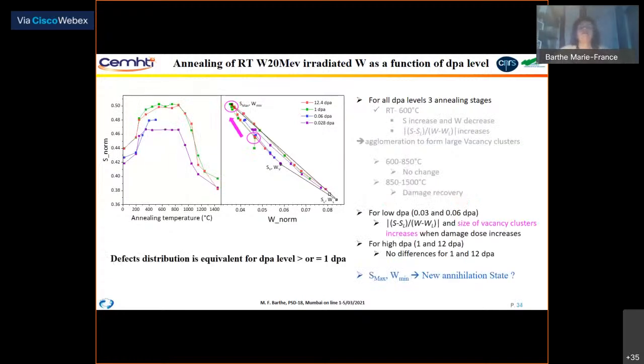So we can see that for low dPa, that means 0.03 and 0.06, the size of vacancy clusters increases here. And for the high dPa, that means 1 and 12, there is no difference in this behavior. So we can say that defects distribution was equivalent when the dPa level is higher or equal to 1 dPa. So it confirms that there is a saturation of defects distribution when we reach so high dPa.